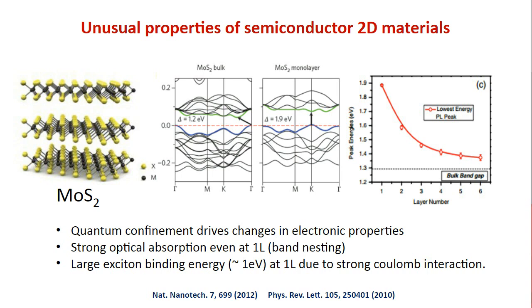Such changes are driven by a process called quantum confinement, and we don't have to worry about that. This is just one of the things that's happening when you go from a bulk MoS2 to a single layer MoS2. There are also other things that happen. The gap character, which is denoted by these arrows in the middle figures, changes from an indirect gap to a direct gap. As you can see in the single layer MoS2, the arrow is vertical, so that's a direct gap system. And for the bulk MoS2 band structure, the arrow is pointing to the left. That is an indirect band gap system.